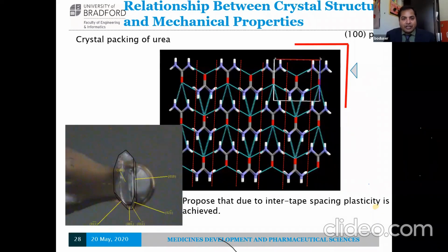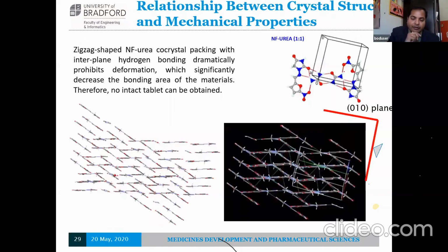If you look at the urea crystal structure, what you see is some interlayer spacing, which offers some kind of cushion. Once you apply pressure on the 100 plane, it offers a cushion that could resist it. Whereas with the co-crystal structure, it has formed an interlocked structure, where if you apply pressure from any particular direction, the 010 plane or the other side, the crystals are quite brittle and are bound to break. So that's how we could relate crystal structure to the mechanical behavior of the co-crystal in this instance.